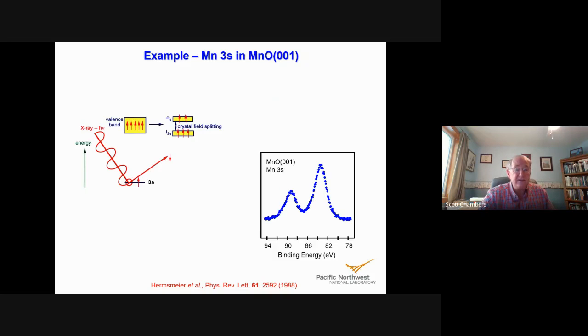So in the valence band, because of the octahedral coordination of the oxygens, the crystal field splitting kicks in, and the T2Gs are lower in energy than the EGs for the manganese d orbitals in the valence band. And so in order to think about how this might play out in photoemission, we need to think about angular momentum coupling schemes. And it turns out that for manganese, because of its atomic number, the best way to do this is to use Russell-Saunders coupling.